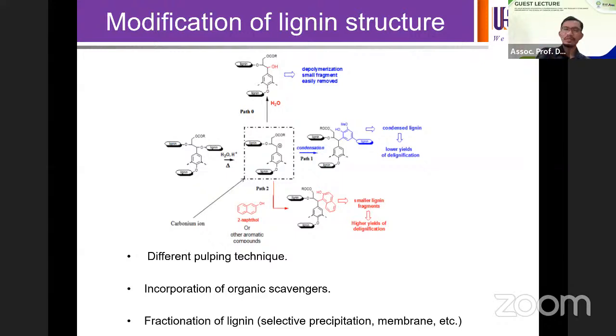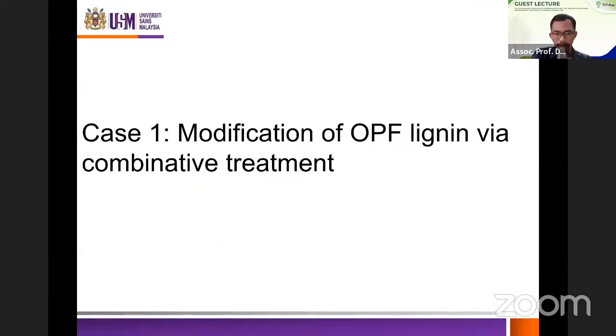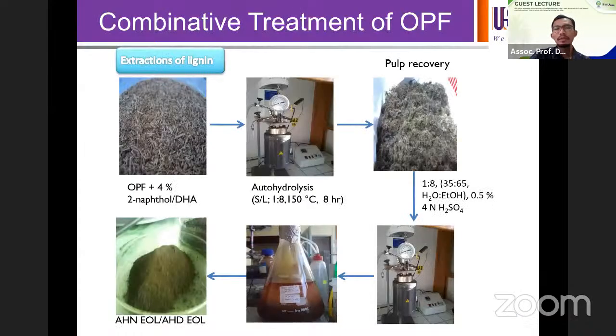And finally, we also concentrate on modification by means of fractionation of lignin using selective precipitation, ultrafiltration methods, and so on. So the first modification we did was a combinative treatment using the scavenger. What we did was soak the biomass with the chemicals, which in this case is 4% of 2-naphthol or dihydroxyanthraquinone. We perform autohydrolysis so that most of the hemicellulose will be extracted out, and hemicellulose can actually jeopardize